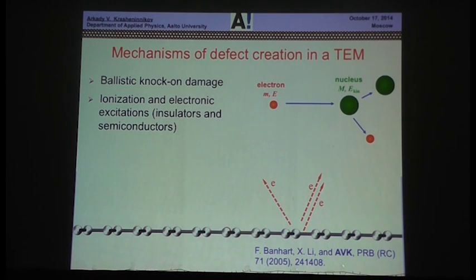By the way, if your sample is not very well connected electronically to the environment, you may get a positive charge. Dmitry has a very nice demonstration with boron nitride tubes. This is a bit counterintuitive, but remember that electrons have energies of about 100 kilovolts. They go through atomically thin targets, and they also knock out secondary electrons. This may or may not give rise to a Coulomb explosion and electronic excitations, and production of defects this way. The third channel is beam-induced etching.